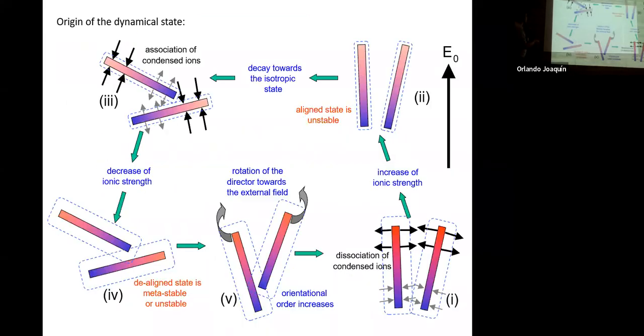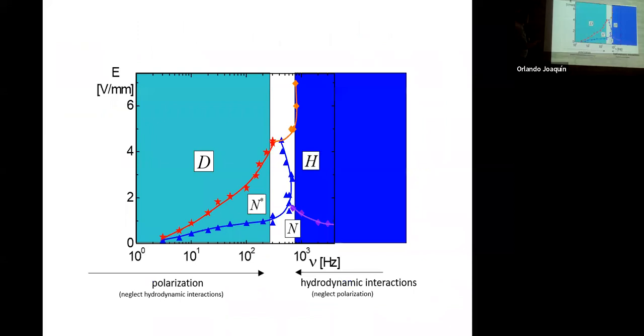That's a good question. You can change two things here: you can change the salt concentration and keep the FD concentration fixed, for example, and then it looks completely different. Because if you change the salt concentration, you change the ionic strength, right? So if you add salt, the extra salt concentration due to dissociation of condensed ions is very, very small compared to the salt you already have, and then it will have no effect. So you will lose all these conditions at higher salt concentration.